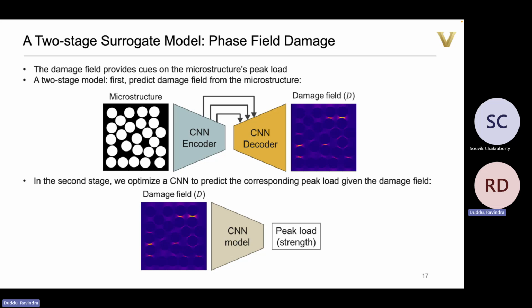It's an image to image predictor. So we go from microstructure image to damage field image. And remember how in my phase field data, I record the peak load, I record the damage image. I take the FEM data and interpolate that onto a pixel grid, 512 by 512, and I generate these damage images. I use that for training and then testing as well.